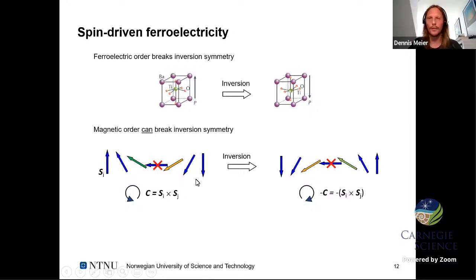You see a cycloidal structure on the left-hand side, this red cross here, that's our center. And when I go from the left to the right along the spin structure, you see that they are rotating in a counterclockwise fashion. We can express that via the spin product and the chirality of the spin structure. And if I now apply the inversion operation, that's what I try to illustrate here, going from the left to the right, you see that the spin, which is yellow on the left, will then change position, go where the green spin was before, and the green spin will go where the yellow one was before.